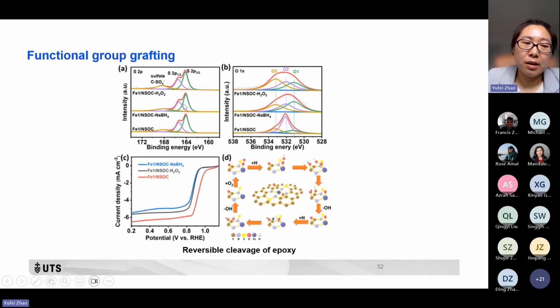And then we try to investigate whether the epoxy group indeed affects the catalytic performance for ORR. We use a chemical treatment on this material to destroy this epoxy group and see whether the performance will change. After the treatment by oxidation and reduction, we found for sulfur there is almost no change here. But for the oxygen, the epoxy group's dominant trend has decreased. The epoxy group has been changed to other oxygen groups here. And accordingly, we can see the performance decreases very obviously after the oxidation and reduction. So that means this epoxy group indeed plays quite an important role to further boost the ORR catalytic activity of this iron, nitrogen 4, and sulfur 2.